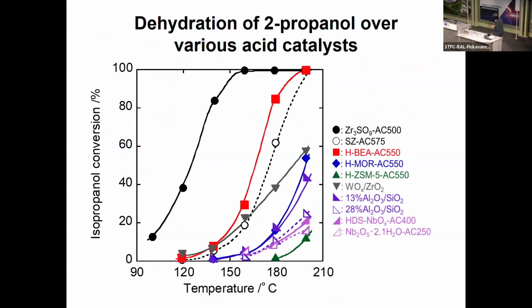Here is a comparison with other typical solid acid catalysts. There are many, but as you can see here, the sample we prepared in this process is much higher than other typical solid acid catalysts. This is so remarkable. Even the material we prepared is much superior to the conventionally prepared sulfated zirconia. Again, I have to emphasize that the conventional material has to be calcined at high temperature. But in our case, we don't need it. Just put this material into the reaction, and you can expect acid catalysis.